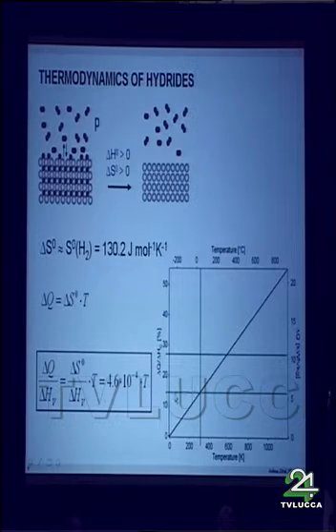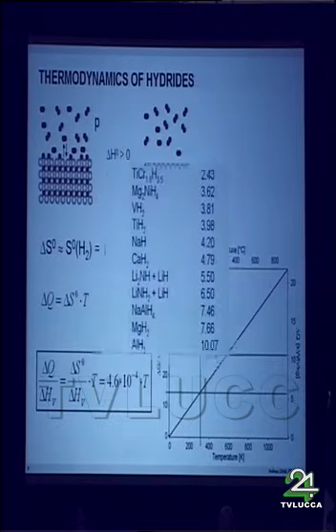And that means as long as we are working at a temperature below the equilibrium temperature, the ambient temperature, our environment can provide the heat to desorb the hydrogen. As soon as our working pressure requires a temperature above the environment, we have to deliver this heat to the system. And here in this figure you can see how this ratio increases with temperature. For example, if we are working at something like 300 degrees centigrade, so about the magnesium hydride temperature, it already requires almost 30% of the heating value just to desorb the hydrogen. And this is, again, a general parameter of all systems which make a gas-solid transition of the hydrogen.